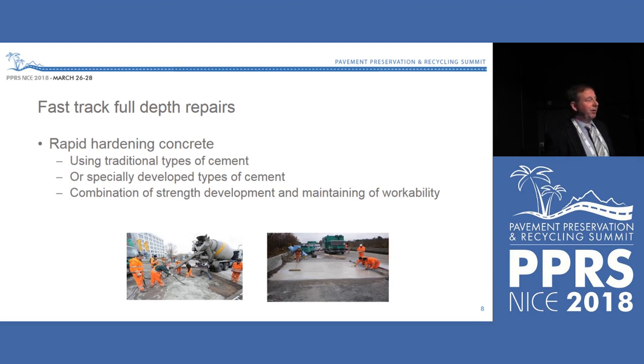Let's say the important message is forget what people always think, that the concrete needs 28 days to harden before the traffic can drive over it. No, even with a normal, good quality concrete mix that we use, even after 4 to 7 days, the road can be reopened to traffic. When it has to go faster, using normal materials, the normal types of cement which are available, it is possible to reduce that time to 2 or 3 days. Well, often the challenge is not getting the strength, but it is the maintaining of the workability.